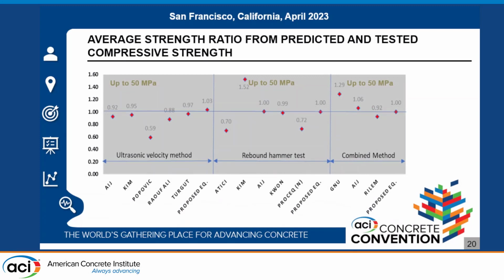In order to analyze and compare the models presented before, the following graphs were prepared, which show us the effectiveness of each one. Here we can see the prediction ratio of each one of the proposed equations and the previously cited models. For example, in the case of the ultrasonic velocity method, we can see that the model of the Architectural Institute of Japan, the Turgut model and the Kim model have very good prediction ratios, as does the proposed equation.